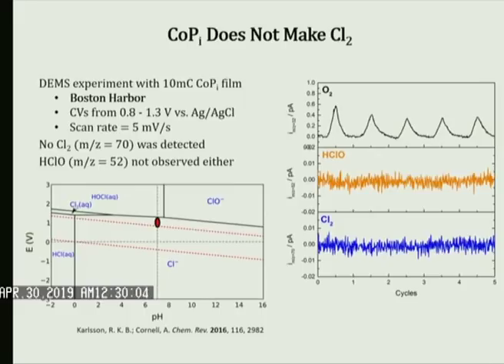So then, this is our newest data, there's chloride in the water. So if he puts the mass spec at chlorine, if we see chlorine being generated as he scans, we should see an upward rise. And you can see it's perfectly flat. And the other thing, if you make chlorine in water, you can make hypochlorite, which is bleach. And you can see it's absolutely flat. And these spikes are the oxygen. So this is the mass spec set at oxygen, hypochlorite, and chlorine. And you can see this thing is totally selective for O2 generation.